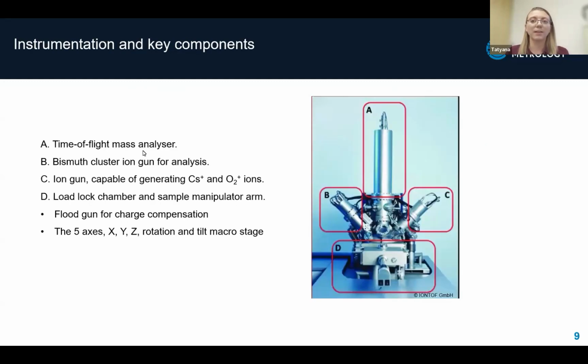Now let's explore the key instrumentation components. The time-of-flight mass analyzer is shown in component A. The bismuth cluster ion gun, which serves as a primary source, is component B. Component C shows a sputter gun capable of generating both cesium and oxygen ions. This versatility allows us to optimize the analysis depending on whether we are looking for positive or negative secondary ions.